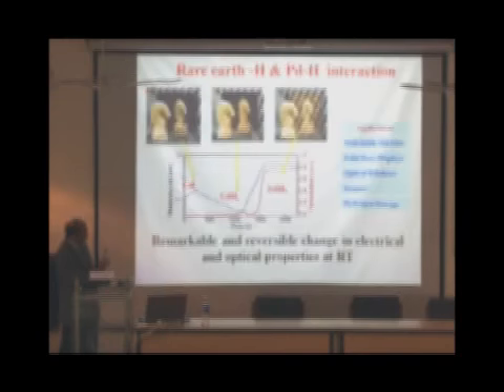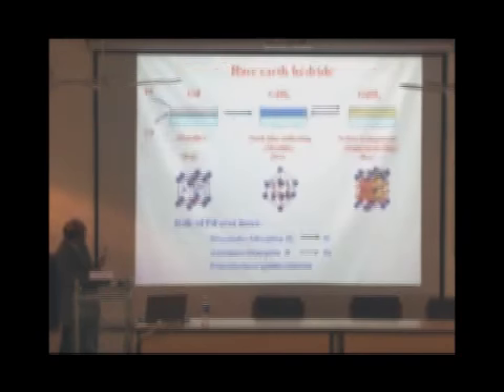And this is what happens. When you have a conventional rare earth material, and normally in most of the switchable mirror devices, it is covered with a palladium overlay, which I will describe, what is the need of palladium. And when we put hydrogen, it goes from metallic state, in this case we have taken the example of gadolinium, it goes to gadolinium dihydride. And when you put more hydrogen, it goes to a trihydride. And if you remove this material from hydrogen, it will come back to dihydride state. And thus from dihydride to trihydride, one can go back and forth.